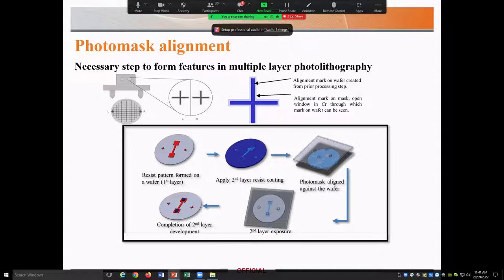In a mask aligner, the square and cross system is very commonly used for alignment marks. The first reference marks are generated on the surface using the first photomask, and then these will be used to align to subsequent layers using the complementary alignment marks.